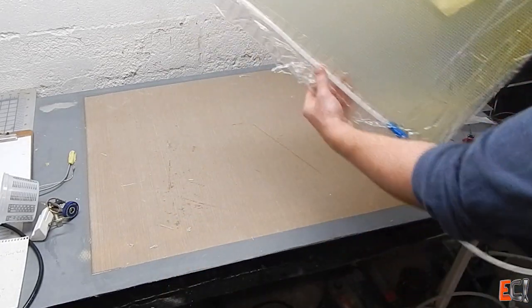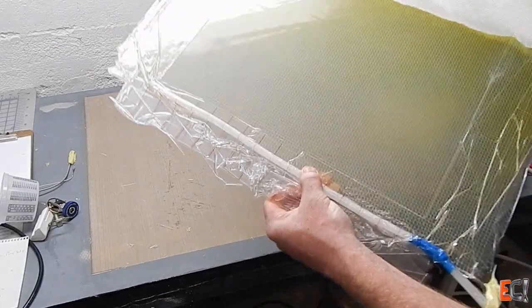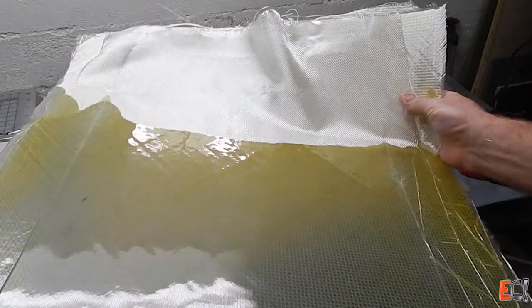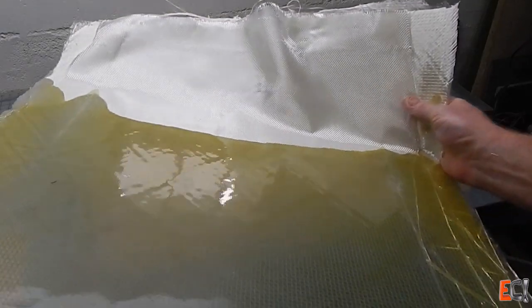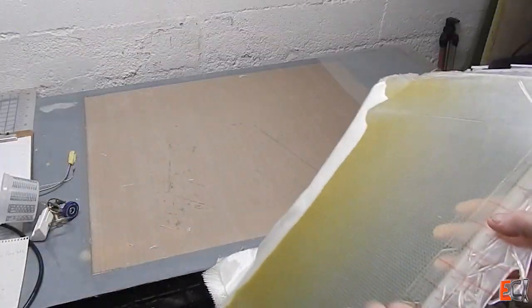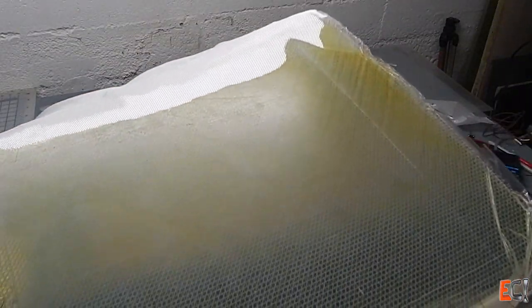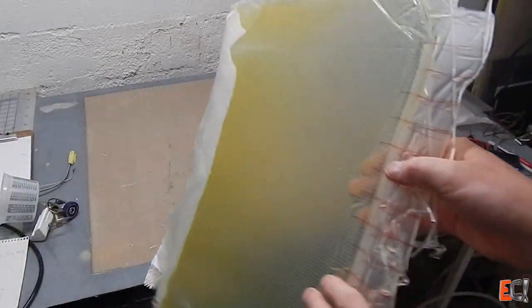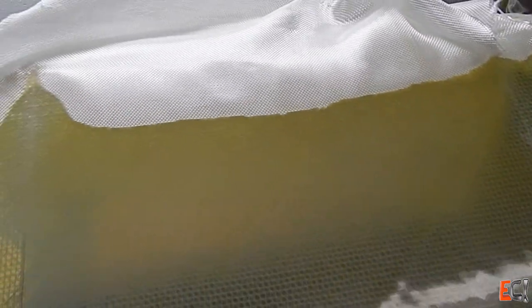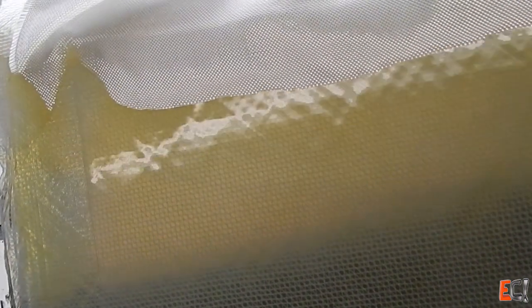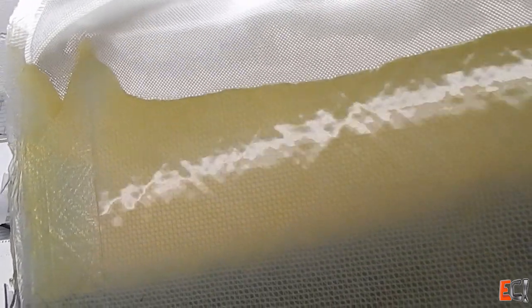Once the caul plate comes off, there's the nice shiny surface that the caul plate leaves, and also, because it's a thin, wiggly caul plate, the bundles of fiber printed through on the surface, where the bundles in the biaxial material were not super even. A stiffer caul plate would have pushed that out, but here we just really wanted to see what was going on and be able to look through and have it optically really nice.